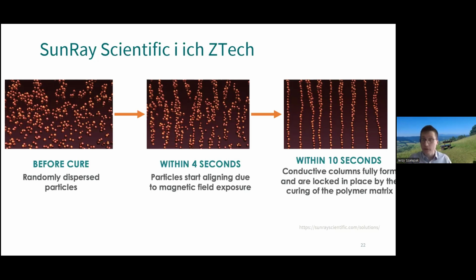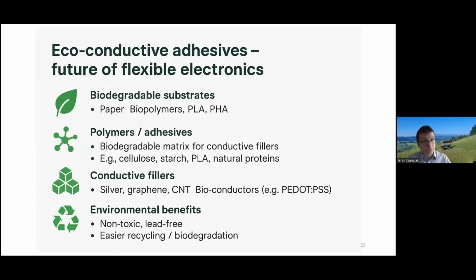And we don't have any risks concerning short circuits. You can apply the adhesive on the whole chip. The current will work only in the Z-axis anyway. The adhesive is also claimed to be a very flexible one, allowing for work in e-textiles or even, after some adjustments, with liquid wires. The main issue here, and I'm once again mentioning the holy grail, is that it's not that sustainable. Although the curing temperature can be easily reduced below 100 degrees.